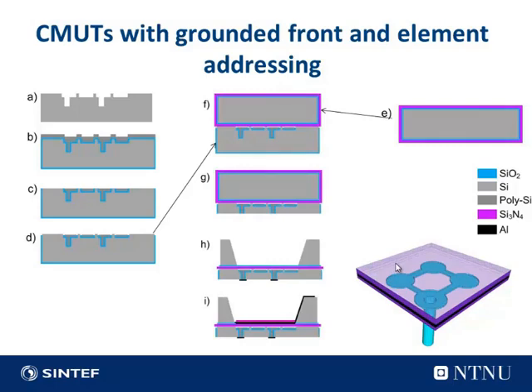We bond the two wafers with fusion bonding, a high temperature anneal process, and this is the bonding step, and then we etch back to reach the vias. The oxide is not shown there, but then we grow a new isolating oxide, pattern the aluminium on the backside, and then we do the cavity etch on the front side to reach the membrane. So at this stage, the thickness of this area is approximately 25 microns. Then we deposit the rest of the membrane stack, the aluminium and PECVD nitride.